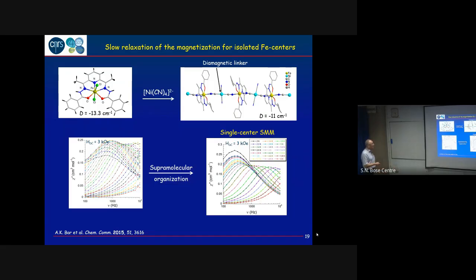So what I was telling is sometimes the slow relaxation is limited by the intermolecular interaction that makes the relaxation very fast. But you can organize your molecules in the solid by doing a little bit of chemistry, and this is just a molecule I showed before. So you take this one, this is the behavior. You organize it in a solid. So now you space the paramagnetic molecule, you space them in the chain, but you space them also interchain. And then the behavior you get is this one.